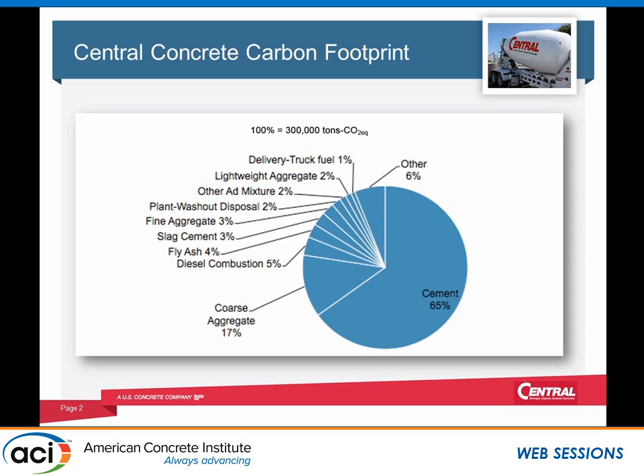But if you actually look at it, our delivery truck fuel, which is essentially our material coming in, and then the diesel combustion of our ready-mix trucks going out, you add those two together, that's only 6%. Now we are using a lot of slag cement and fly ash, but with that, cement is still a large piece of our carbon footprint. And so we started looking at ways to reduce the amount of cement. There are a couple of different ways that you could go about doing that.